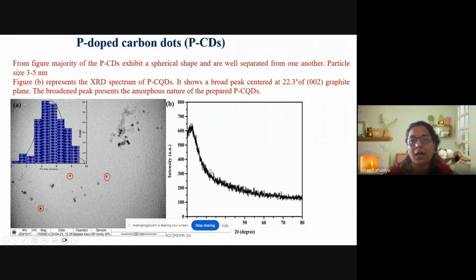Further, the P-doped carbon dots, where we use phosphoric acid as the P-dopant. This is the TEM image, and this is the XRD pattern. The TEM image shows a narrow particle size distribution of 3 to 5 nanometers, and the broad peak at 22.3 shows the 002 graphitic plane.